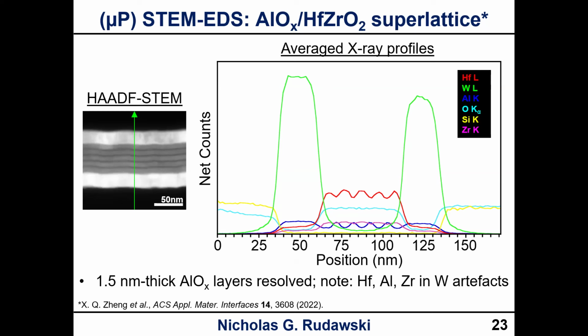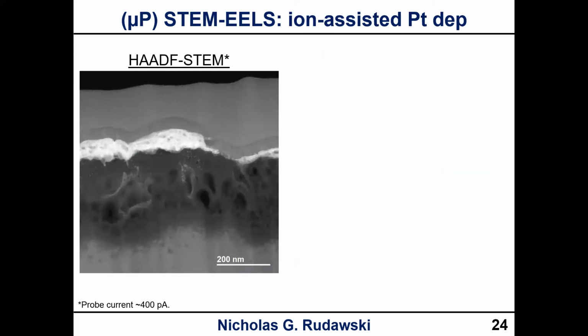So again, part of the lack of sharpness of the interface in the profiles is due to the fact that you can see in the layers they're not perfectly flat. So when you're integrating from side to side, that's going to be reflected in that. But you get a nice noise smoothing effect if you do that over a wide left to right field of view. And then last but not least, I did want to show some EELS data here,